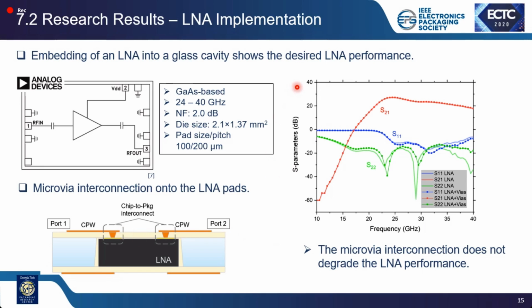And if you look at the frequency response or S parameters, we can easily tell that we don't see much difference between the frequency response with microvia interconnects and without microvia interconnects, indicating that the microvia interconnection does not degrade the LNA performance. This is quite important for RF or 5G millimeter wave packages, and also low loss system interconnect as well.